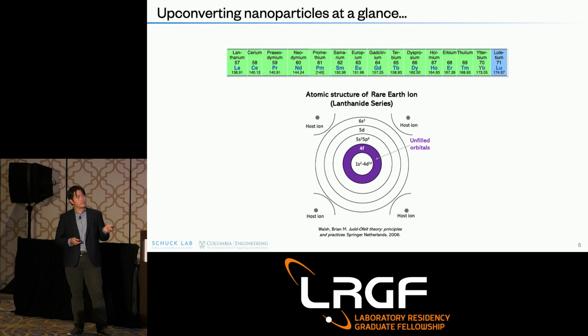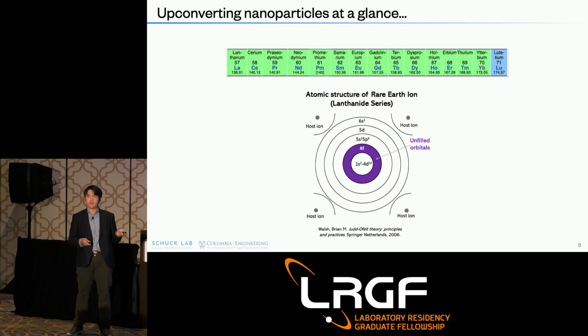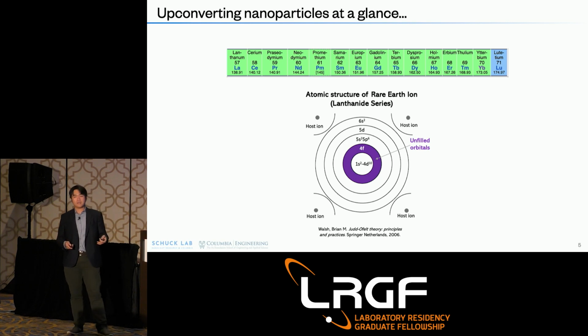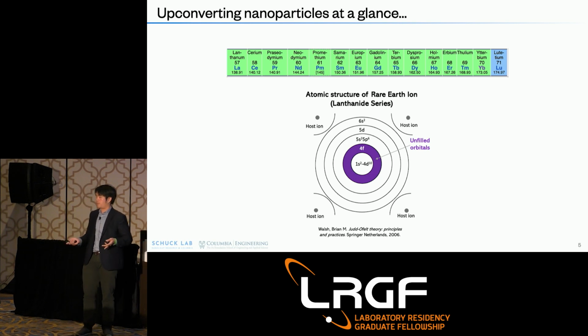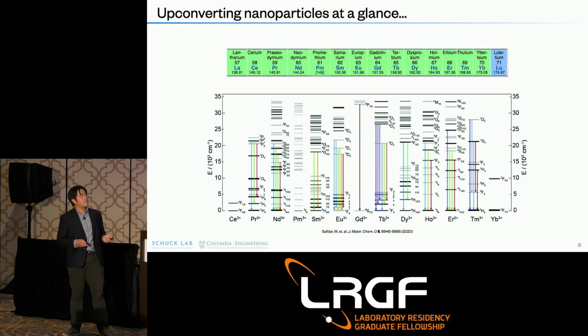And secondly, because this orbital can host as much as 14 electrons, you can get many interesting Coulombic and spin-orbit interactions, allowing you to host states that range from the infrared out to the UV. And lastly, just to harp on the spectroscopic point, these materials also have long-lived states. The 4F transition is parity forbidden, meaning that they tend to reside in the state for about microseconds to milliseconds, and they're unusually bright. Again, perfect for a spectroscopist to investigate.